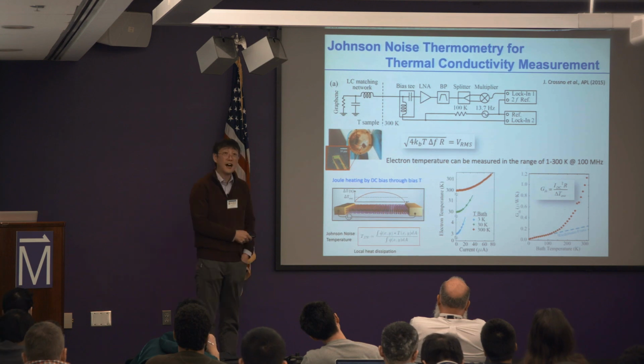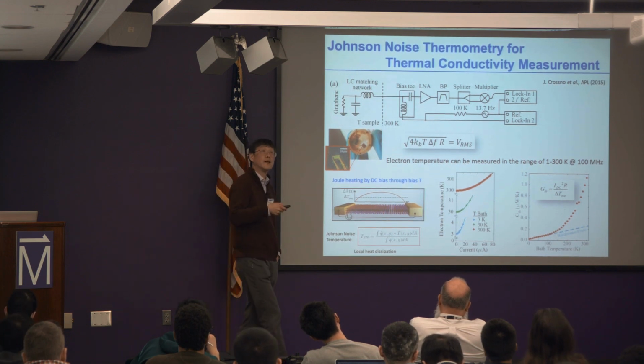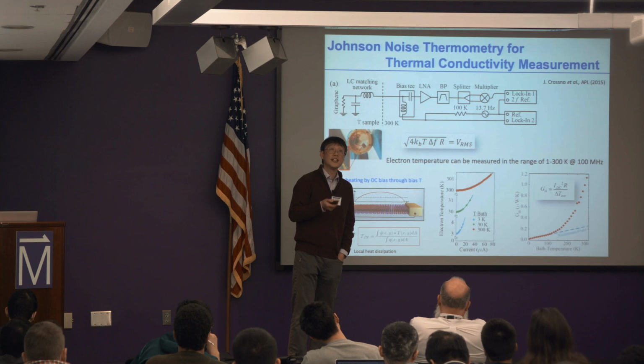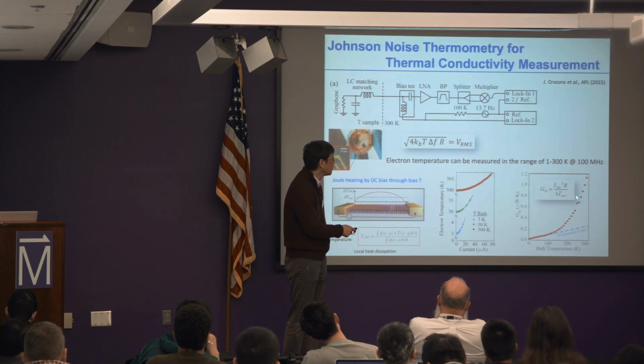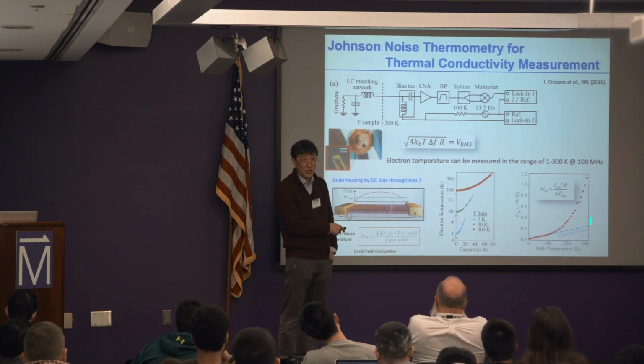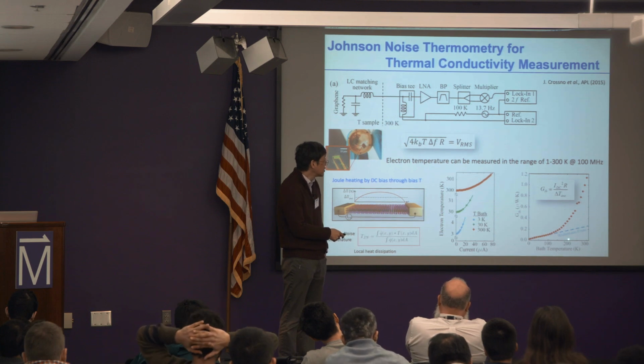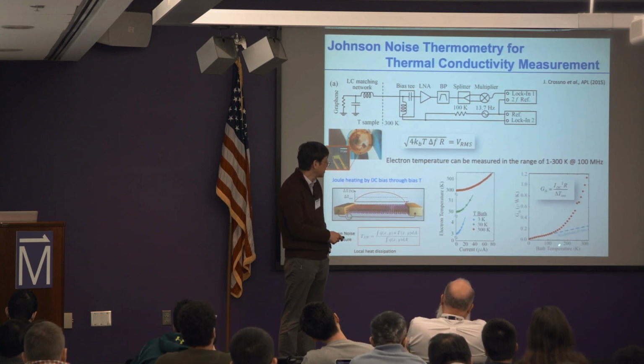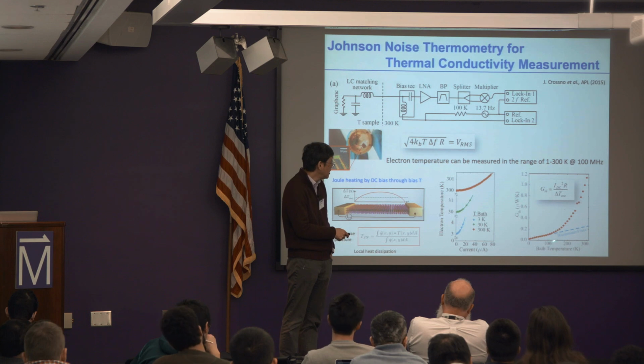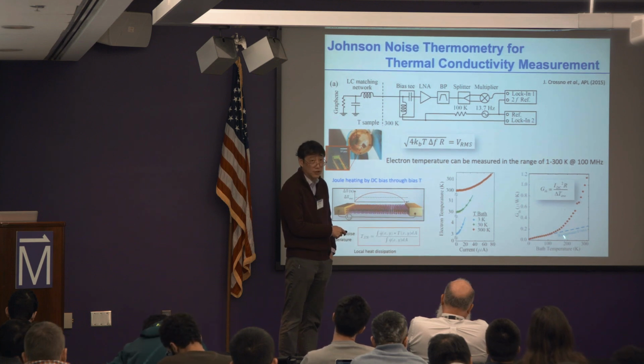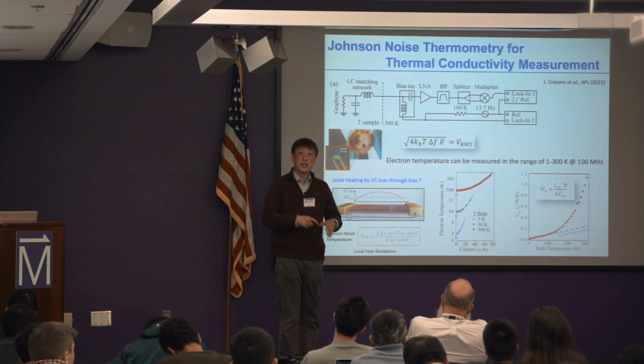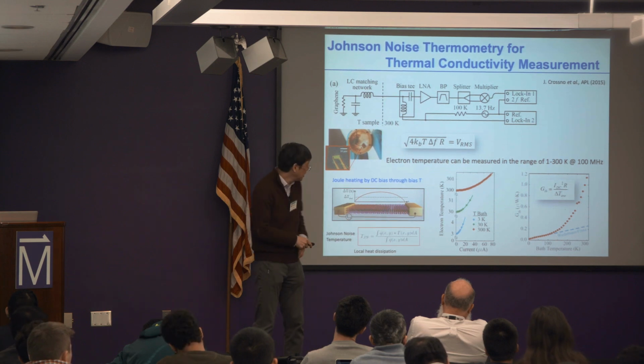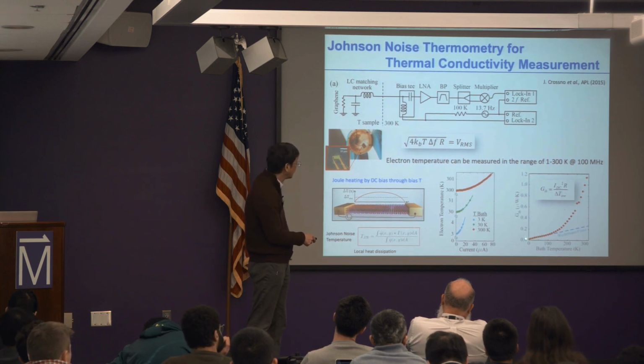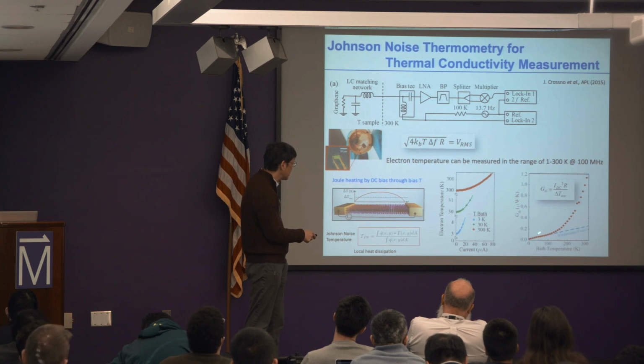Part of the reason is that the electron-phonon coupling becomes stronger at higher temperature. So heat is not staying in the electronic system. It starts to leak through the phonons, where the phonon contribution to the thermal conductivity sets in. So we are measuring some combination of electron and phonon contributions, right? So we already see that with this experimental technique, at least at this size of sample, we need to stay below something like 150 Kelvin. Of course, if you change the device design to be even smaller, we can push this temperature even higher. So that's a limit we can see.